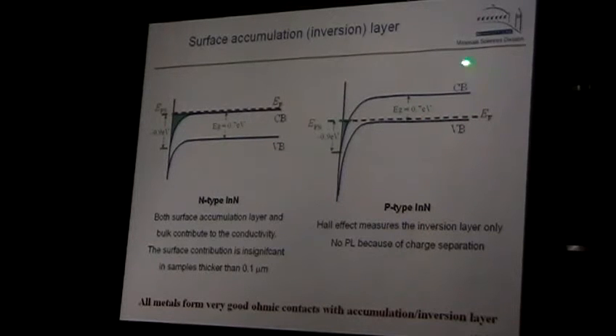And say you dope the material p-type, so your Fermi energy in the bulk, inside the material, is close to the valence band. However, on the surface it still inverts, so it's inversion, because in this case the surface is still donating electrons. And so if you want to do anything with this p-type, measure the Hall effect or measure p-type properties somehow, you always have this n-type layer on the surface which really makes your life difficult. And this is one of the still remaining big issues for this technology, the surface inversion layer.